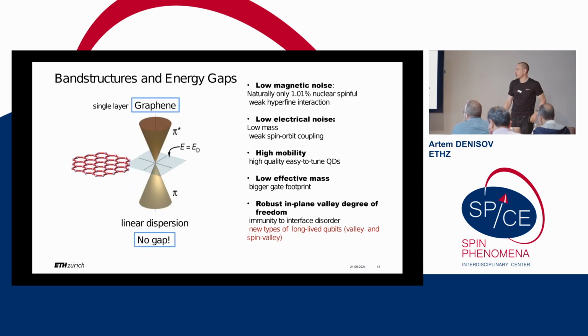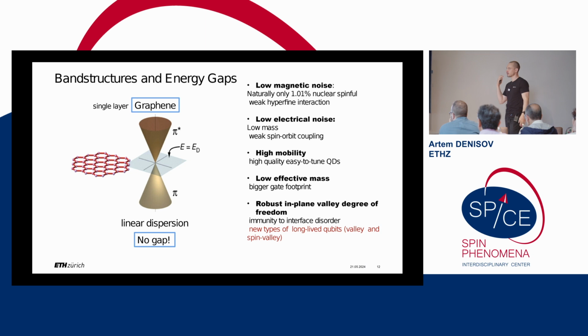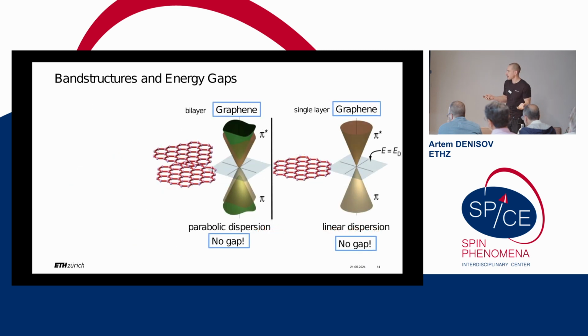So, all right, when you think about, okay, I want to make a qubit, I want to make a quantum dot out of graphene. Graphene is not a semiconductor, graphene is a semi-metal. The only point where it has a zero density of states is the charge neutrality point. So it's impossible to open a gap in single-layer graphene. And if you have no gap, you cannot confine your charge carriers into the quantum dot, meaning that there is no qubit. So the way to overcome it is to use not a single sheet of graphene, but a bilayer graphene, of a Bernal stack.